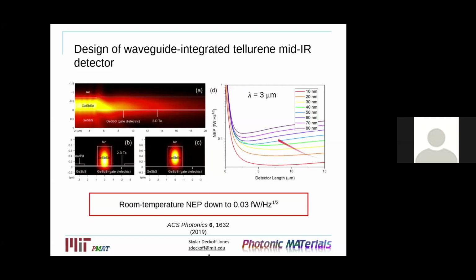But we see with these parameters, we can get an optimal device performance for thinner flakes, 10 nanometers, with short, small devices around 7.5 microns long. And the most impressive thing is we see very, very low noise equivalent powers, which are a couple orders of magnitude better than existing photodetectors based on III-V materials.